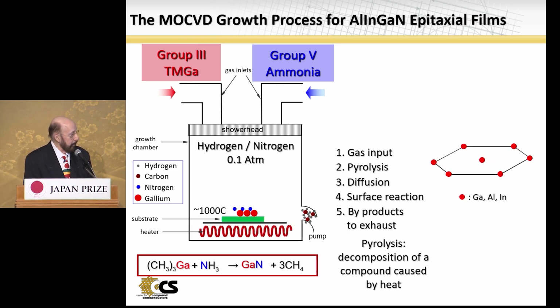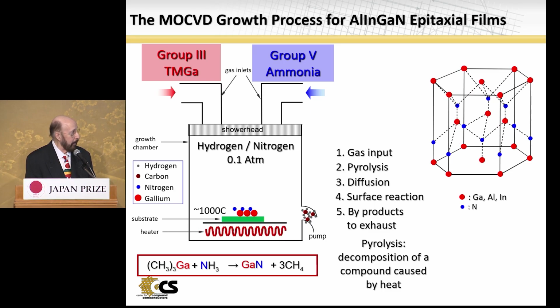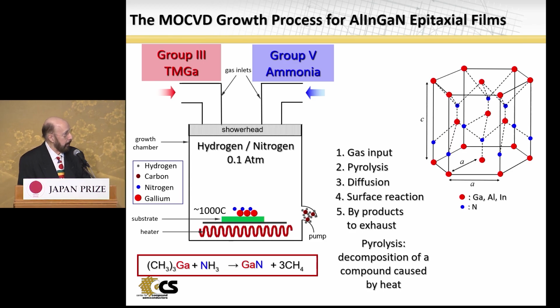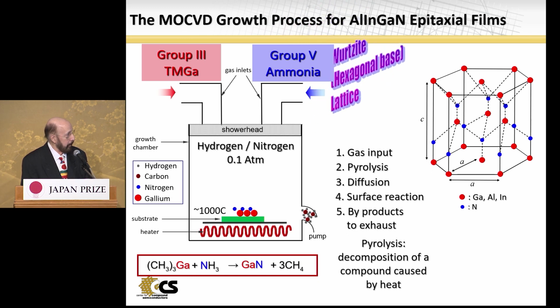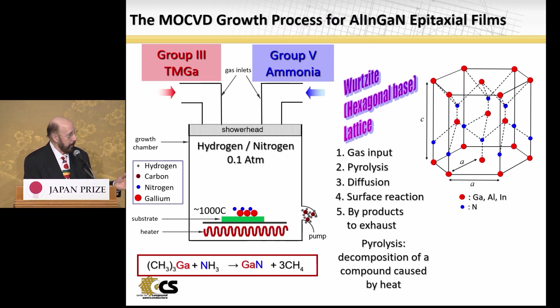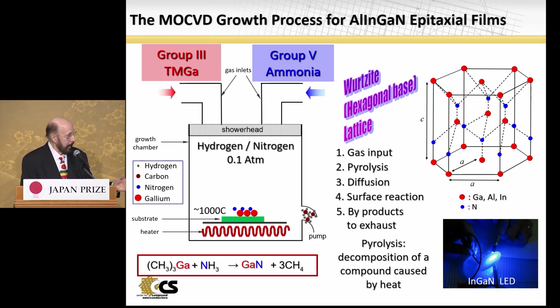So we begin with a layer of gallium typically, and then add nitrogen, gallium, nitrogen, etc., layer by layer, growing this crystal. In this particular case, it's a wurtzite crystal, and can be used to grow the quaternary. If you replace gallium with aluminum and or indium, you can create a quaternary or a ternary. This is an example of an indium gallium nitride ternary layer excited by light showing that LED emission can be achieved.